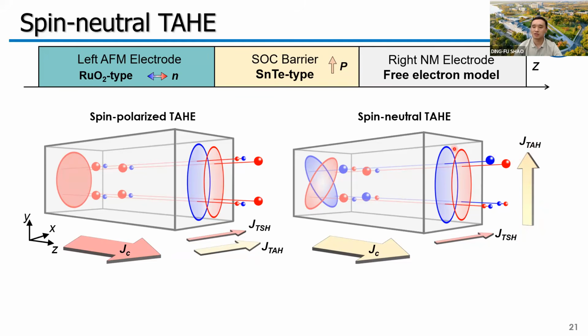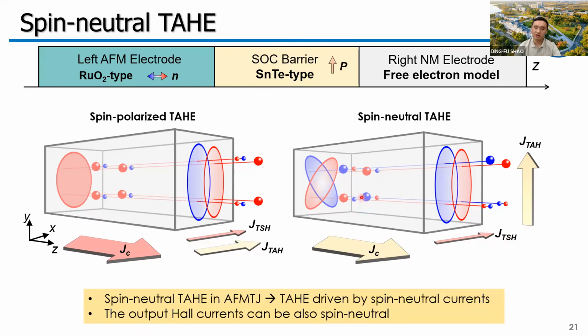But if we consider spin, we find in the left half, we have mostly spin down electrons. In the right half, we have mostly spin up electrons, which generates a spin Hall current along the x direction. So in this case, the tunneling anomalous Hall current and the tunneling spin Hall current are perpendicular to each other, which means the tunneling anomalous Hall current is purely spin neutral. So we have both driving current and output Hall current spin neutral, which is completely different from the conventional expectation of the anomalous Hall effect, where both driving and output currents are spin polarized.